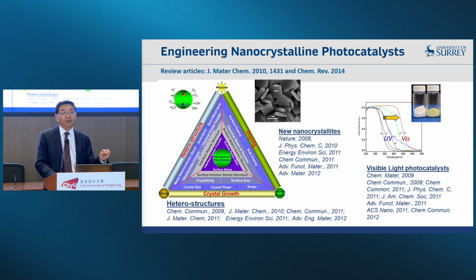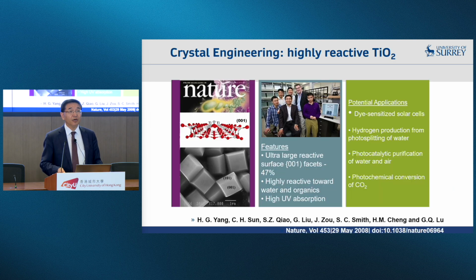So we've been doing this for a long time, and we have developed an understanding of how to optimize the fundamental properties of the nanocatalyst, the photocatalyst, by doping, by heterostructuring, and by crystal engineering. These are the three methodologies that drive towards the center. Doping will improve the surface redox sites, and of course heterostructuring, with different types of oxide and metal oxide, will give you interfacial atomic structure optimization, and therefore the interfacial carrier transfer property will be improved. And of course, through the crystal size, phase, and shape, the surface intrinsic atomic structure can be modified, and therefore you control the surface sites, or the surface state, sorry.